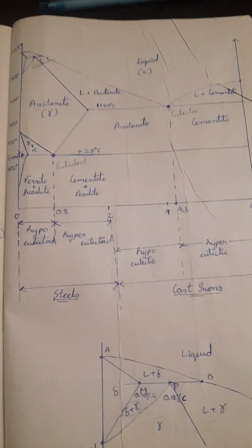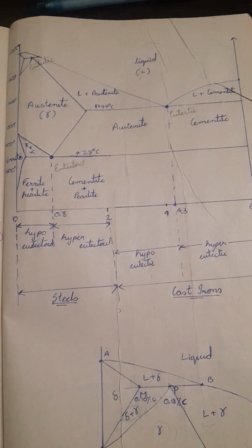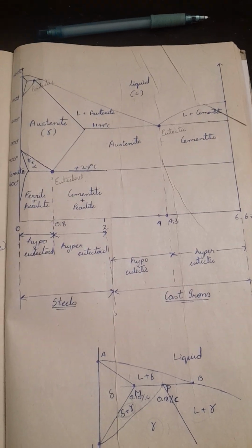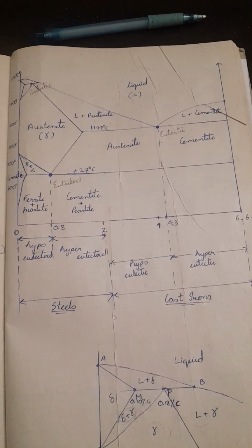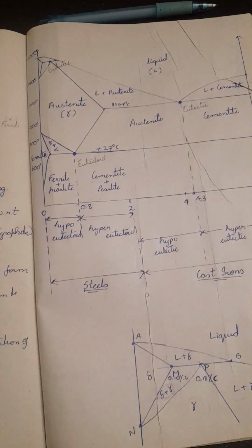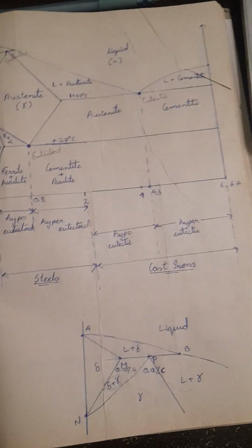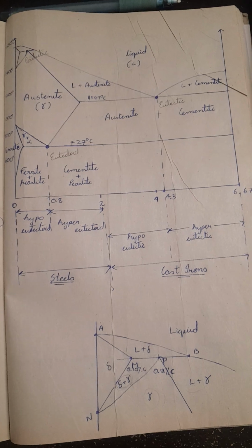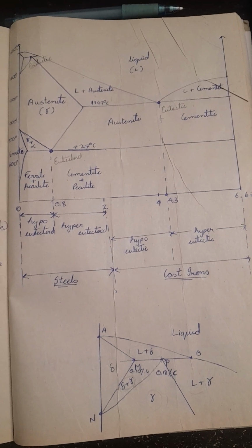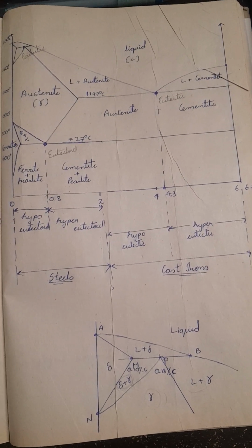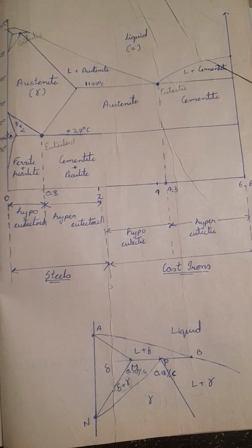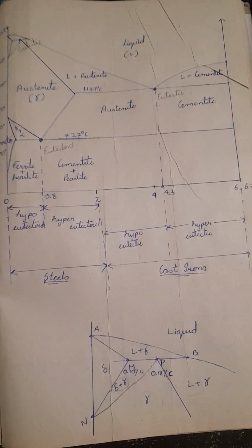But if you have a look at the iron carbide diagram, Fe3C, that is iron carbide, decomposes into iron and carbon, typically graphite, over a period of time. For example, at 1300 degrees Fahrenheit, iron carbide decomposes into iron and graphite, but it takes a lot of time. Hence we are just considering it as an equilibrium diagram, but technically it isn't.